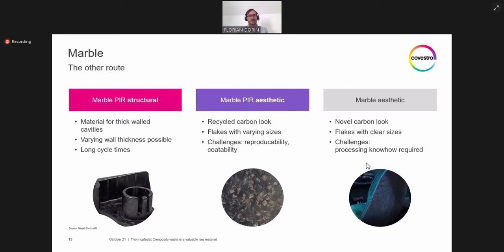Usually this can be used for thick-walled cavities with quite varying wall thicknesses. And you have a good variety of wall thicknesses, of performance, and so on, where you can really use the structural properties of the carbon fibers in those parts. However, you have to be aware that these thick wall thicknesses, which you can realize, require long cycle times. So for products where cycle time is maybe of less importance, those solutions might work. And this is for the structural applications.